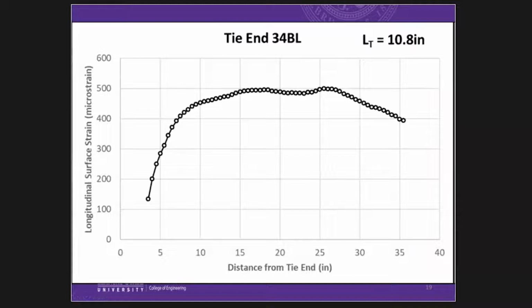And so it's a process that we can actually go out and get many transfer lengths at a single time and characterize the bed and see where we are. It's really easy to get shorter transfer lengths. You just leave it in the bed longer. Higher release strengths give you shorter transfer lengths. We actually helped one of our clients do that. We looked at the histogram and said, you know what, you really should have a little bit higher release strength if you're going to use that same concrete system and wire type.